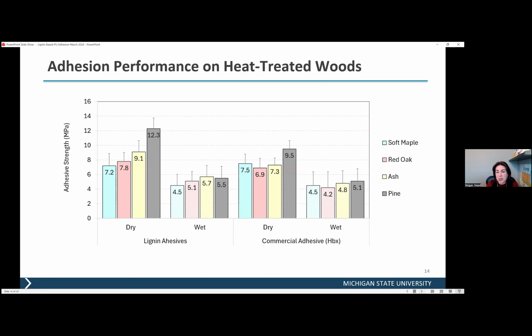The other question we had, as we were talking to one of our industrial partners, was that they were interested in using heat-treated wood. For those of you who don't know what heat-treated wood is, they basically use either steam or oil to cook the wood, similar to how you make French fries, in an environment without oxygen, or with steam. They put that wood at temperatures between 180 degrees C and 220 degrees C. During this heat treatment, there is no chemical involved, just the heat.